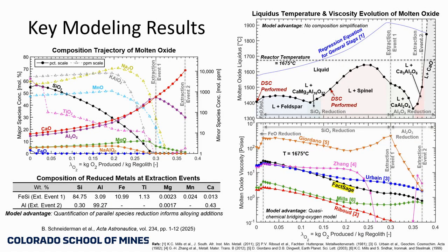So this slide has a lot on it, and I would encourage you to look at a paper we recently had published in Acta Astronautica that Ben led, but it shows the composition trajectory as we move through lambda oxygen, just incrementally removing oxygen and seeing how the system reorganizes. And on the right side, how the liquidus temperature evolves through the reaction, and the viscosity changes, all of which is very important for understanding the process of MRE.